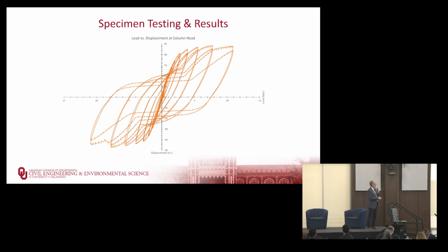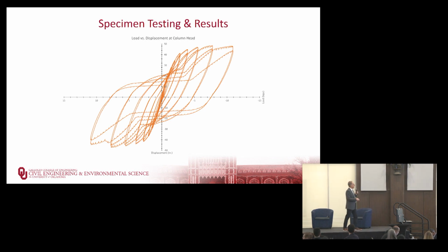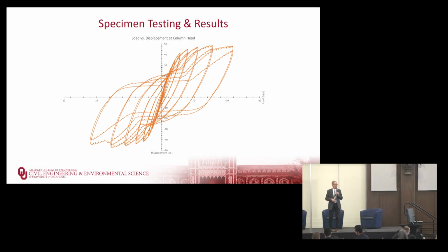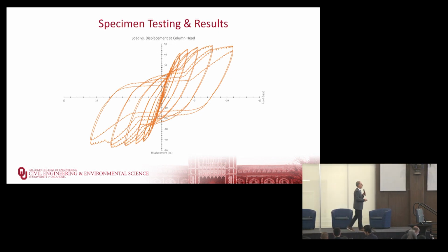We have that same kind of plateau, which all of a sudden we start to straighten out the steel tube when we're pushing it in the other direction. But the interesting thing is with the UHPC, you don't see a drop off, right? You see increasing load, till finally about here, when we're out at about 12 inches, we finally start losing capacity. So completely different, a lot more resilience with the UHPC. And when we open it up, we'll talk about why that was.